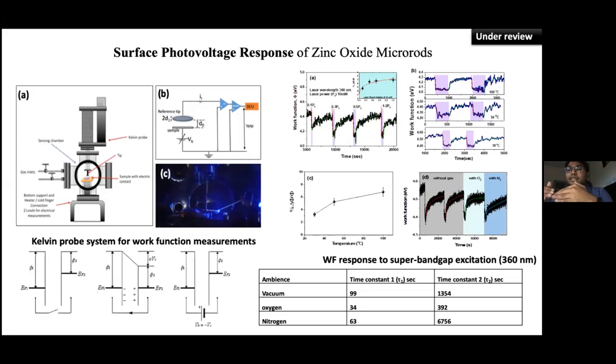However, this raises the carrier level. So this is routinely employed in photo response of ZnO. What we have done here is that we have tried to look at the work function response. People usually look at the current change, and then they quantify whether the sensor is good or bad. But hardly anything is known about what changes the recovery of this signal, because once the photo carriers are generated and you remove the light, the photo carriers are going to get annihilated back, or they are going to be taken by the electronics.